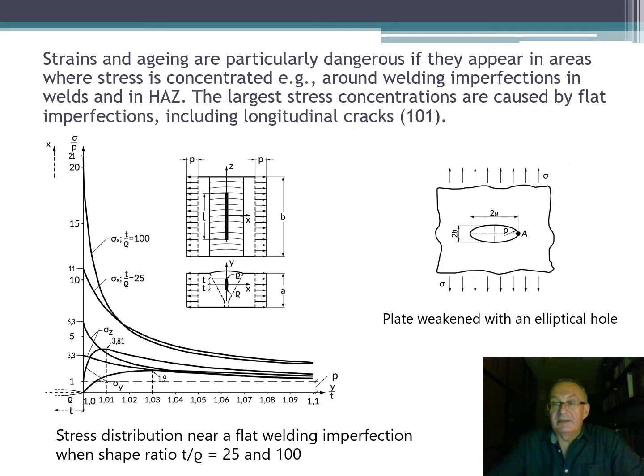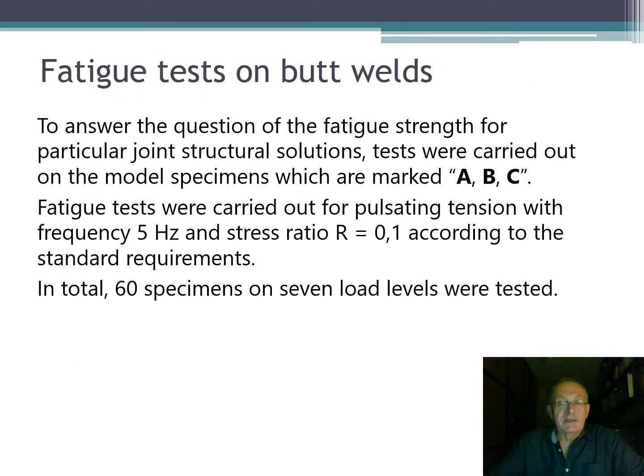This is an example of the basic meaning of such formulas. For the question of fatigue strength for a particular joint structural solution, tests were carried out on model specimens, which are marked A, B, C. I will describe the specimens later. Fatigue tests were carried out for pulsating tension with a frequency of 5 Hz and a stress ratio of 0.1 according to the standard requirements. In total, 60 specimens on 7 load levels were tested.